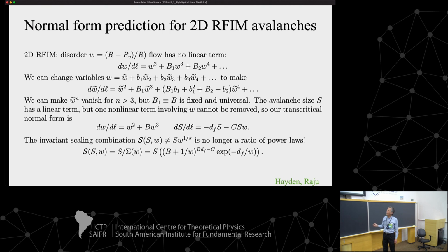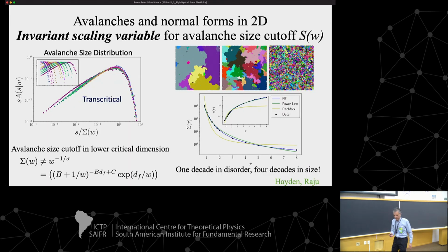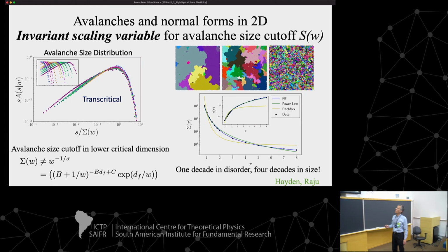So I'm now going to talk. Oops. Yeah. So here's the punchline. In 2 dimensions, we never could figure this out. And here are some 2-dimensional avalanches when the disorder is high, when the disorder is lower, when the disorder is lower. And you can see the avalanche size is growing pretty quickly, as you would expect. There's an exponential here. It's not a power law.